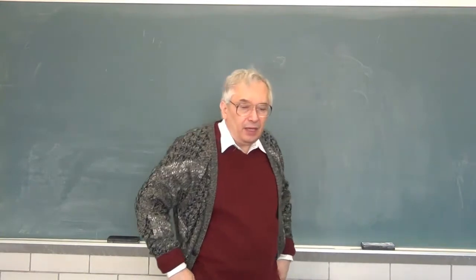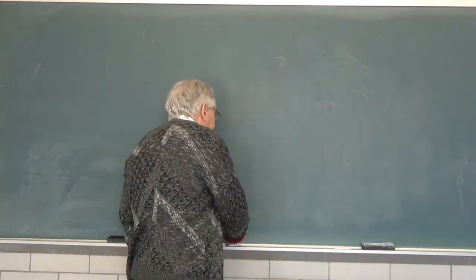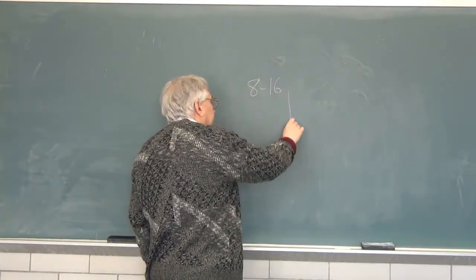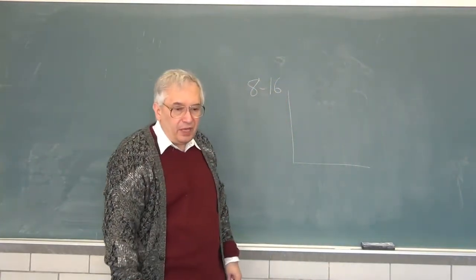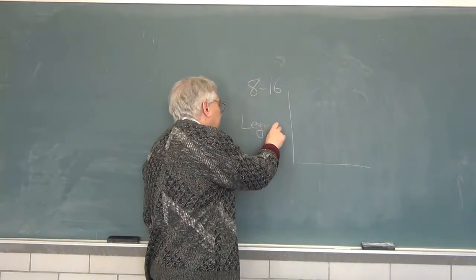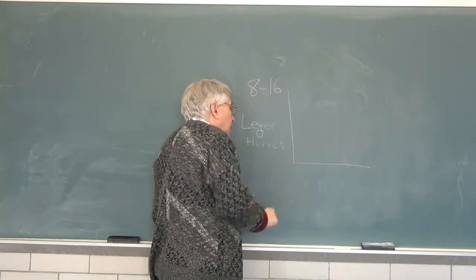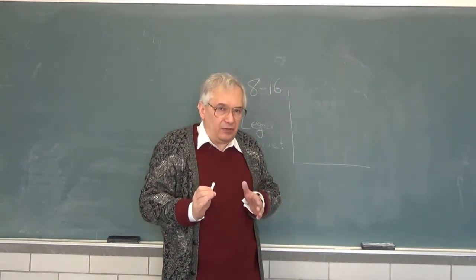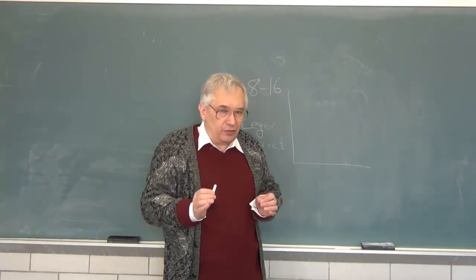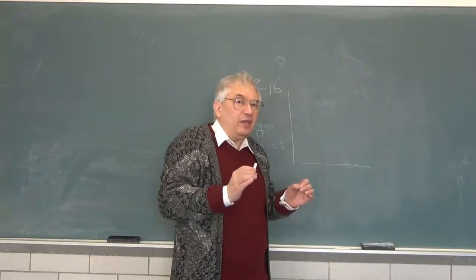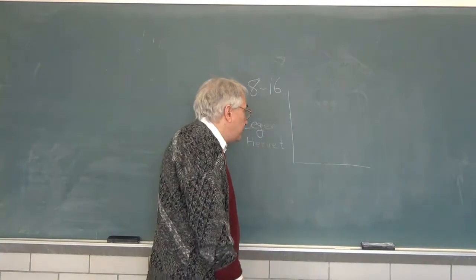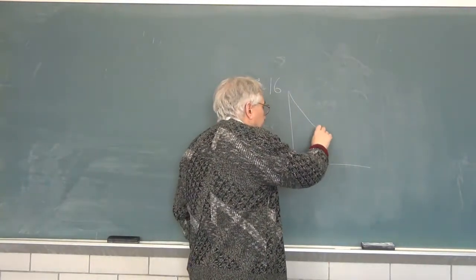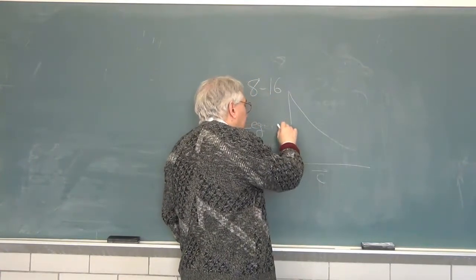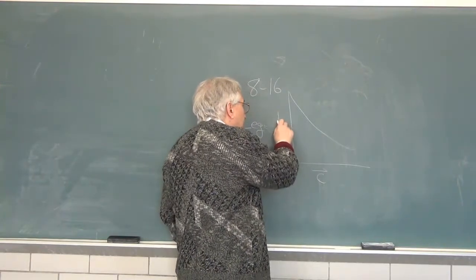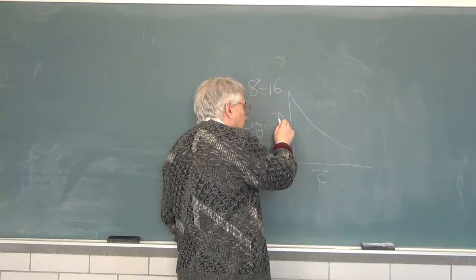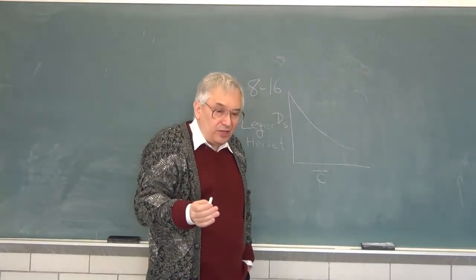So we now chug ahead, and we advance to figure 8-16. And 8-16 is a series of papers associated with names including Leger and Hervé. The graph is noteworthy in particular in that this is more or less one of the first systematic studies of polymer self-diffusion. And the authors also did tracer diffusion. What you observe, if you don't look hard at the graph, is that yes, as you increase the concentration of the matrix polymer, the diffusion coefficient of the probe slows down.